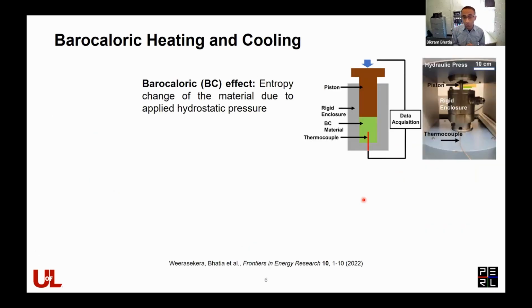What we've been looking at is the barocaloric heating and cooling. So this is based on the barocaloric effect, which hasn't really received a lot of attention. It only started to gain prominence, I would say, maybe around 2019 or so, when there were some material studies showing impressive performance in some material systems based on the barocaloric effect, which is the entropy change or temperature change of a material when you apply hydrostatic pressure to the material.